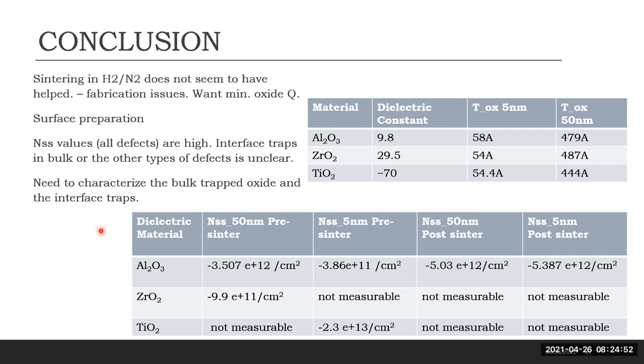The 50 nanometer TiO2 wafer gave us leaky capacitors before and after sinter, though a few of the capacitors on the 5 nanometer film appeared to work. An interesting result, since the 5 nanometer films are the ones that usually give current leakage. We could also look at ALD depositions at slightly higher temperatures to affect the stoichiometry and give better quality films to start with, even if the deposition rates are slightly lower in some cases.